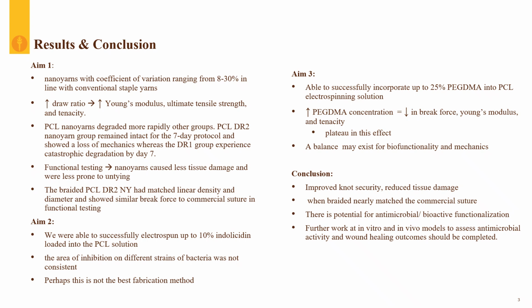For aim 2, we were able to successfully electrospin up to 10% of indolicidin directly into the electrospinning solution. However, zone of inhibition results were pretty inconsistent, so perhaps this isn't the best fabrication method for an antimicrobial nanoyarn. From there, we moved to our PEGDMA PCL blends. We were able to successfully incorporate 25% of PEGDMA into these blends, and with an increased PEGDMA concentration, we had a decrease in mechanics. However, there was a plateau in this effect.